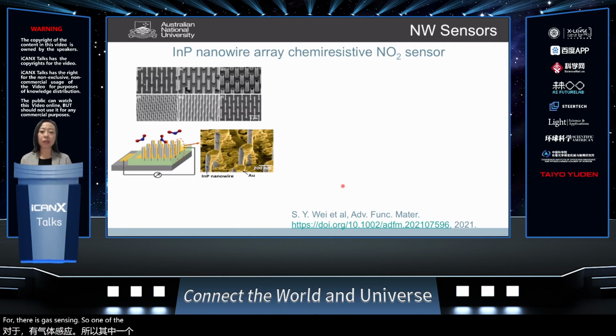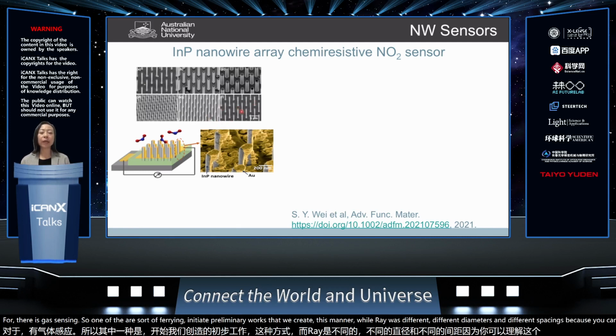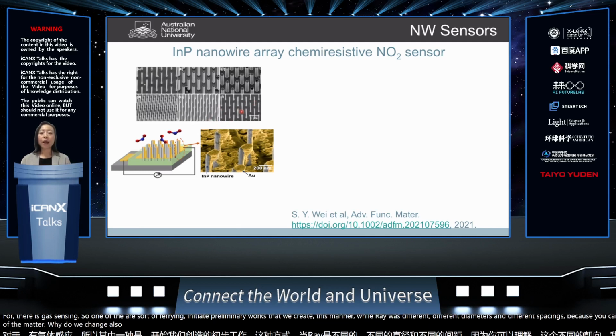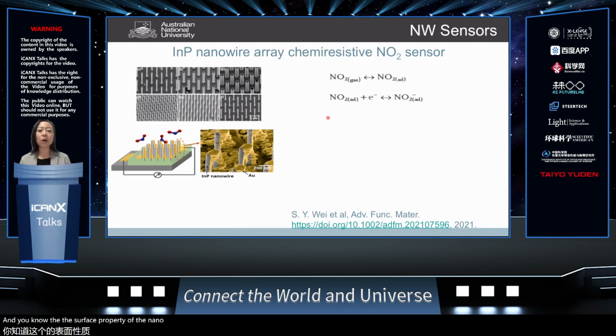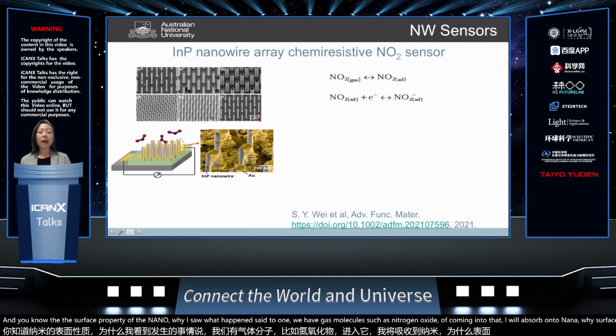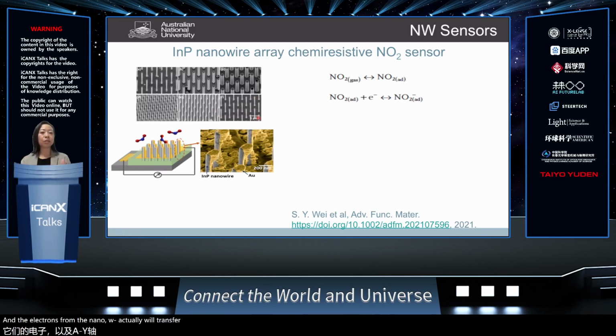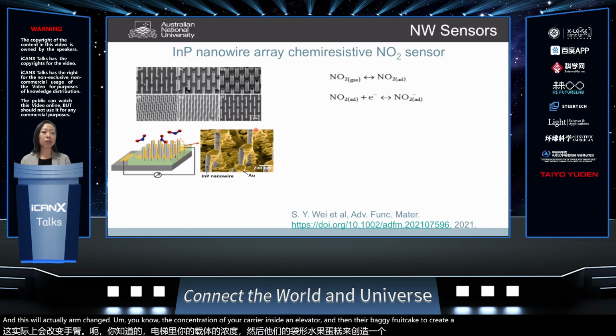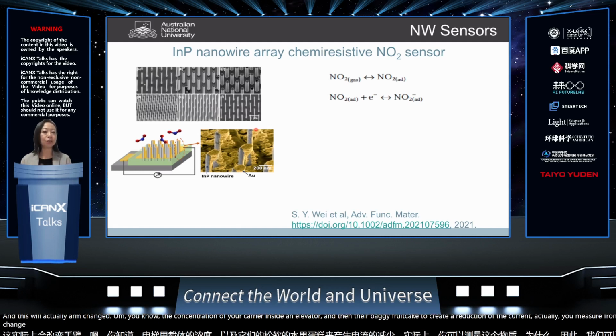In one of our very initial preliminary works, we created this nanowire array with different diameters and different spacings, because with different spacing, we change the surface area of the nanowire, and we also change the surface property of the nanowire. When gas molecules such as nitrogen dioxide come in, they absorb onto the nanowire surface, and electrons from the nanowire transfer to react with nitrogen dioxide and form nitrogen dioxide ions. This changes the carrier concentration inside the nanowire, thereby creating a reduction of the current you measure from the nanowire. So basically it's a conductivity change due to the absorption of the gas molecules.